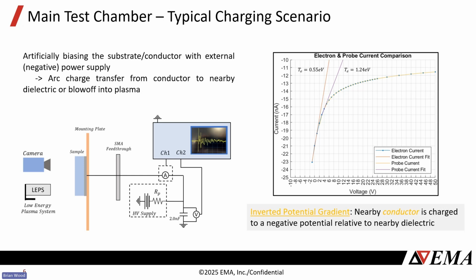So there's always going to be some capacitance contributed from the spacecraft relative to plasma, and that's usually a really low value. But sometimes you might add more capacitance if you know, hey, I'm giving you this sample, but the sample is only a small representation of what it's going to actually be. So say the sample might actually be a much larger sample on the spacecraft. You can only fit so much in the chamber. And so we'll add additional capacitance to try to represent the real LCR components of the sample in the actual spacecraft configuration. And similarly, we also have a voltage probe across that capacitor, and this is just a way to monitor the current and waveform captures.